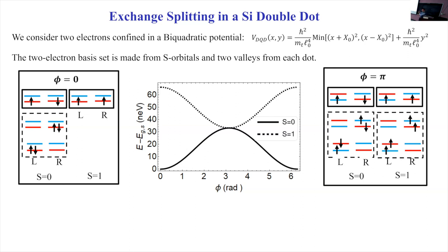Turns out, the exchange contribution from Coulomb interaction follows roughly the same pattern. So now both singlet and triplet states are lowered relative to the excited states, and that gives you a zero splitting between the ground singlet and triplet state. Okay, so that gives you the phase dependence in terms of the exchange coupling.